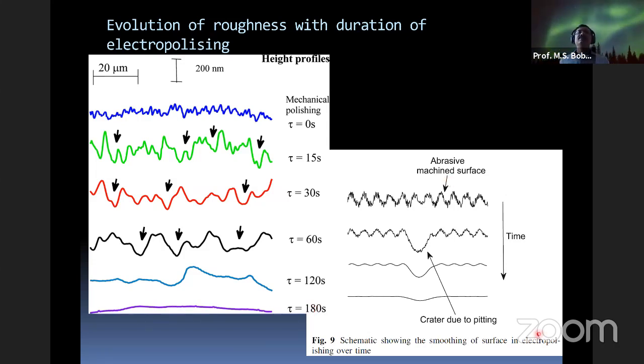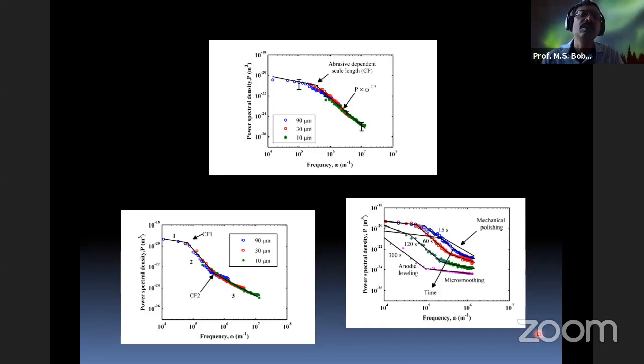What it shows from our study is that electropolishing removes surface wavelengths which are very, very small, whereas mechanical polishing removes surface roughness whose wavelengths are large, decided by the grit size of the grinding wheel or the emery paper which you are using. If you use a finer grit size, it removes roughness up to a smaller wavelength, whereas electropolishing removes roughness corresponding to very small wavelengths. That is, mechanical machining removes roughness at lower frequency or higher wavelength, whereas electropolishing removes higher frequency and lower wavelength roughness. So by combining these two, we'll be able to produce a very smooth surface.